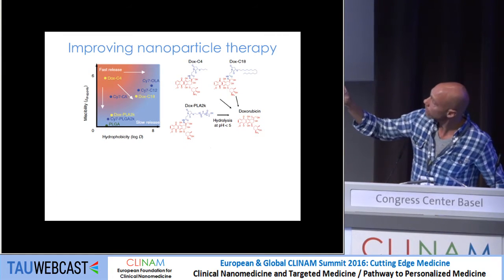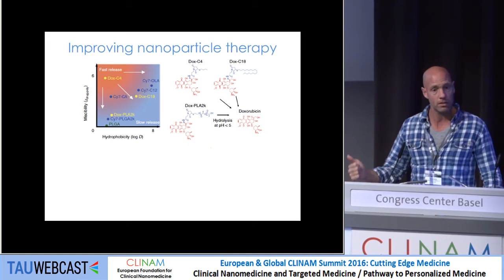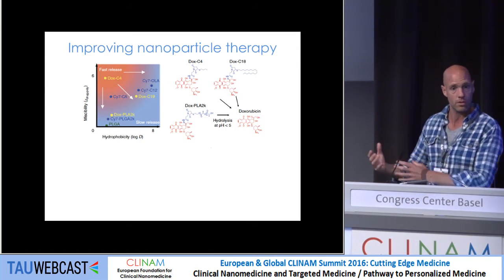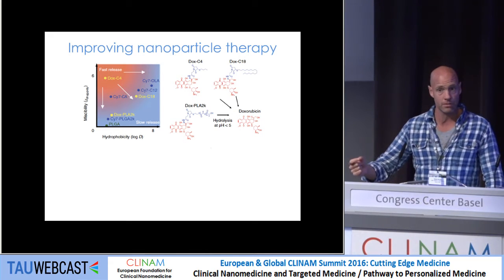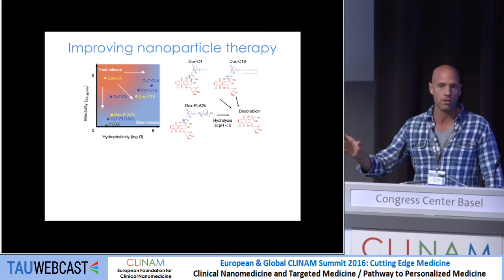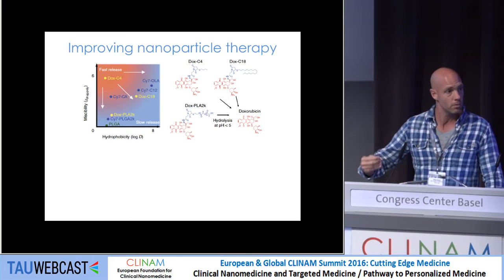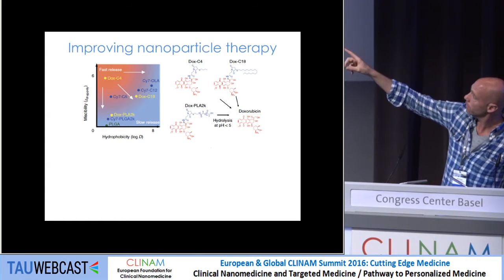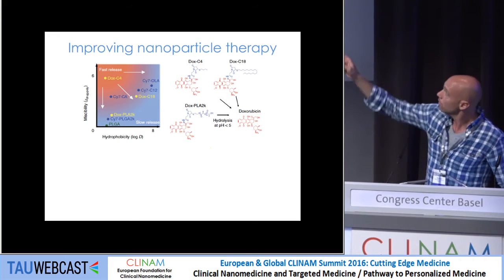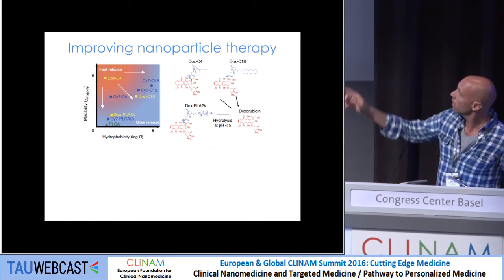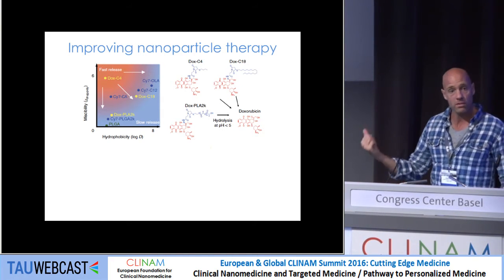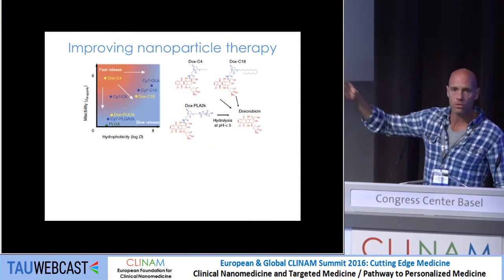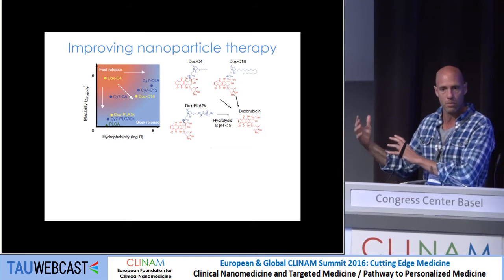The guidelines show that we can increase lipophilicity and miscibility to increase the compatibility of a drug for a nanoparticle platform. The problem is that conjugating functional groups to an active drug may change its therapeutic properties. So we put in place a pro-drug approach, implementing this for doxorubicin with a pH-cleavable linker at lower pH. We link the same groups as for the imaging study, giving different degrees of compatibility. Once these nanoparticles accumulate in the tumor, where there's a slightly lower pH, we ultimately recover doxorubicin — so the functional group does not compromise therapeutic efficacy.